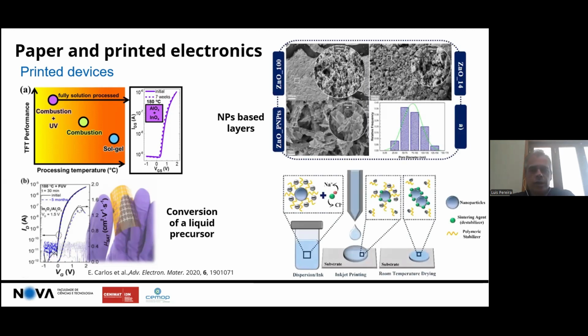Instead of converting a material, you can start from the material itself. So let's go back to zinc oxide and the oxide semiconductor. You can start from zinc oxide already, so you do not need to convert a precursor into zinc oxide. You start from zinc oxide nanoparticles, and you need to deposit them. Here the challenge is another one, because you need to ensure that you form a continuous film, ensuring also a proper percolation between the particles when they are printed or assembled on the substrate. There are several strategies to do that, playing in a very elegant manner like chemical sintering.